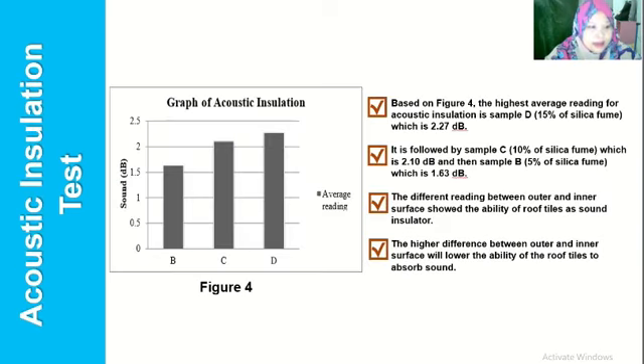Okay, next is the acoustic insulation test. Based on figure 4 here, the highest average reading for acoustic insulation is sample D, which is 15% of silica fume, at 2.27 decibel. It is followed by sample C, which is 10% of silica fume, at 2.10 decibel, and then sample B, which is 5% of silica fume, at 1.63 decibel. The difference in reading between the outer and inner surface shows the ability of roof tiles as a sound insulator. The higher difference between outer and inner surface will lower the ability of the roof tiles to absorb sounds.